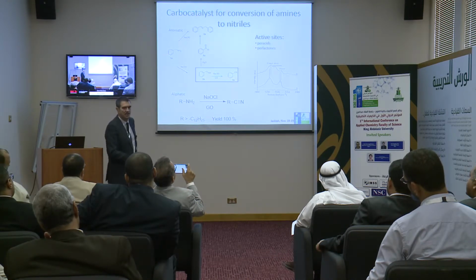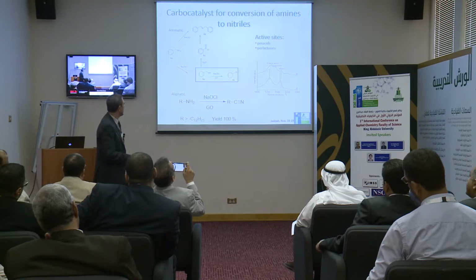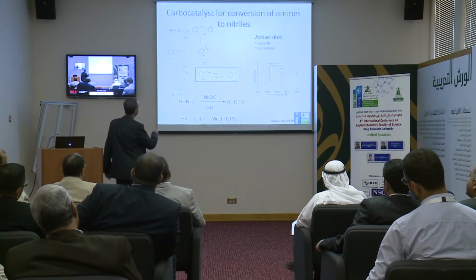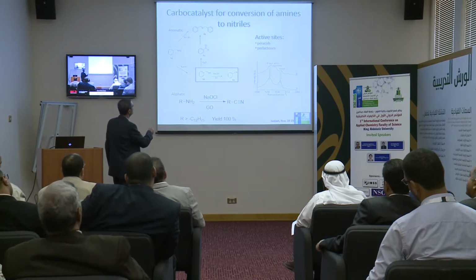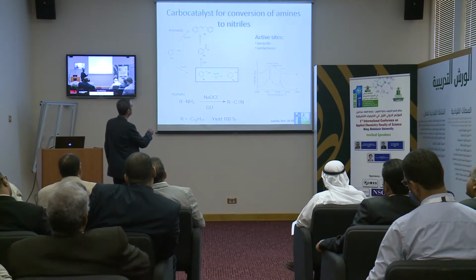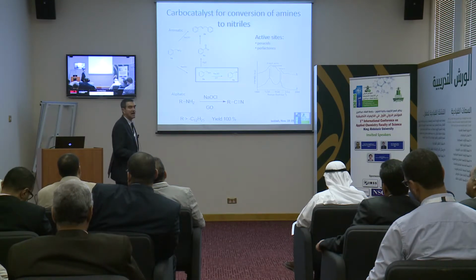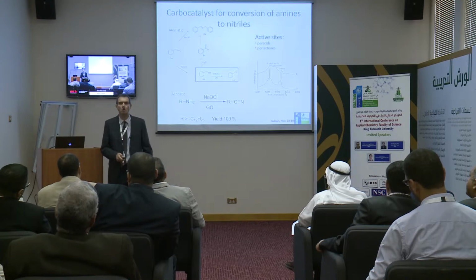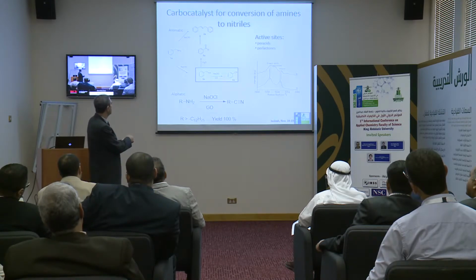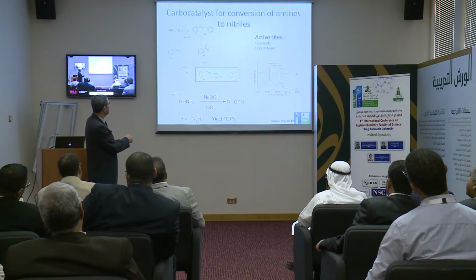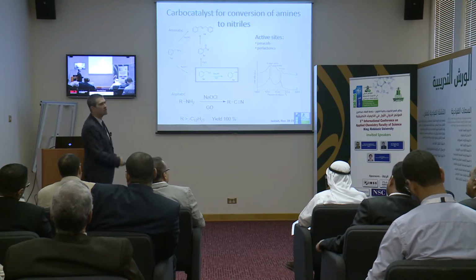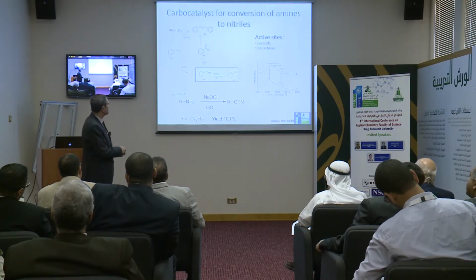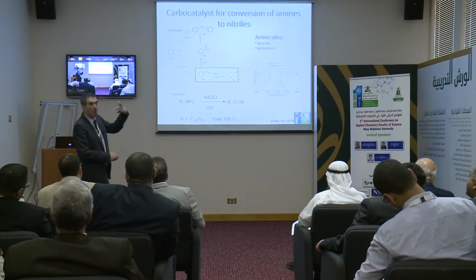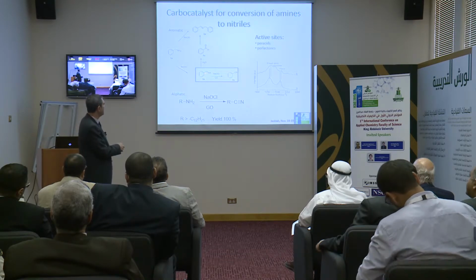It's a reaction that has industrial relevance. And what's happening in this case, we are not using oxygen. What we are using is hypochlorite as oxidizing agent, and it's very interesting because the first process, going from the benzylamine to the imine, does not require catalyst, but what requires catalyst is the overoxidation of the imine to the nitrile.